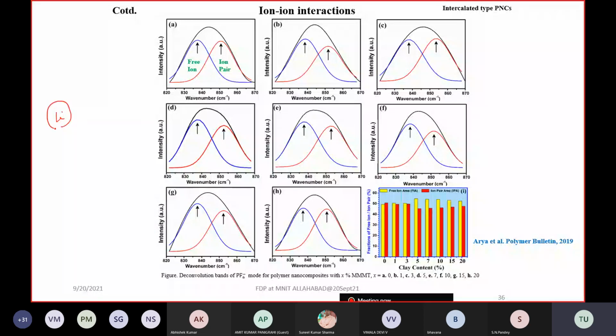Lithium is not going to reflect in the FTIR spectrum. So for that reason, we are going to analyze PF6. PF6 is going to appear because of its bigger size. It is going to reflect in the FTIR, and its range is somewhere 820 to 870 centimeter inverse. So what we found here: if we find the PF6 minus, however many PF6 minus we get in any of these types of composites, the same number you can take as an analogy of the lithium being there.